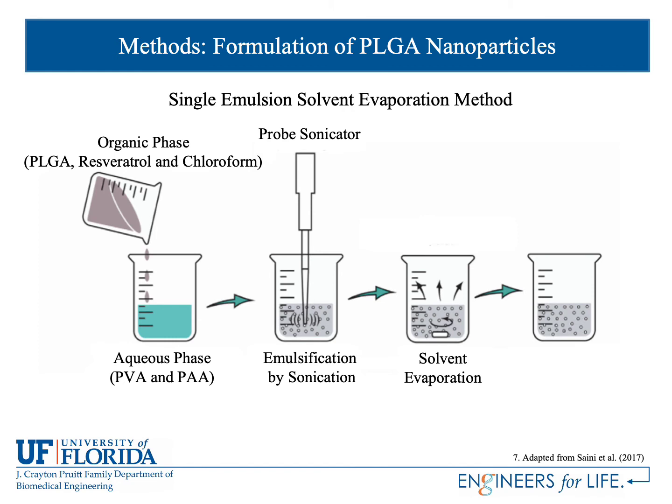Next, we will have solvent evaporation. Chloroform is very toxic to the body, and so we want to make sure that the chloroform is evaporated and left PLGA nanoparticles. Next is the nanoparticle aqueous suspension. Particles are collected through ultracentrifugation and washed to remove stabilizer and free drug. Lyophilization is then used to evaporate the water and leave us with those dried nanoparticles.